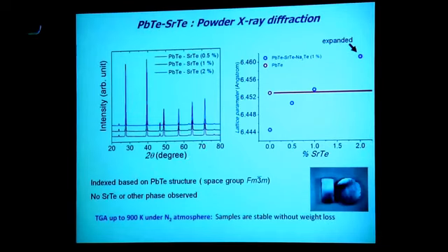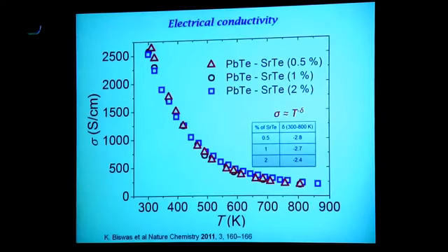Only rock salt structure. However, the lattice parameters respond. So as you raise the strontium telluride, you raise the lattice parameter. So that's good. And then again, it's Vegard's law. It tells you that it's dissolving in the lattice. So here's what these things look like. You can cut the samples to make measurements. These are made by cooling melts and making ingots.